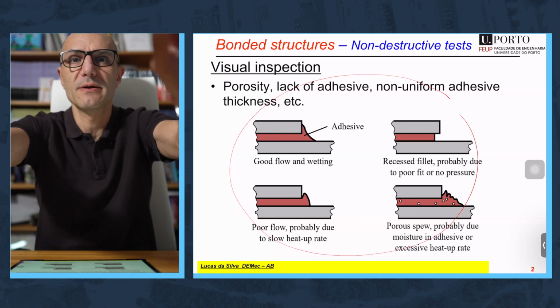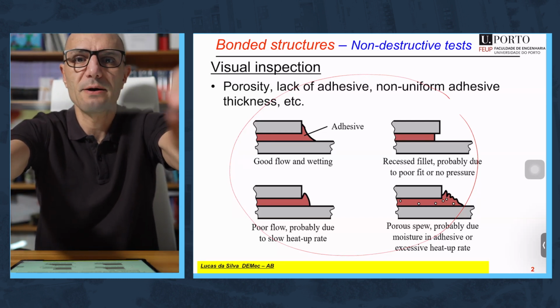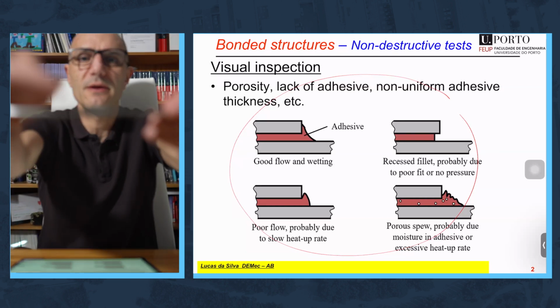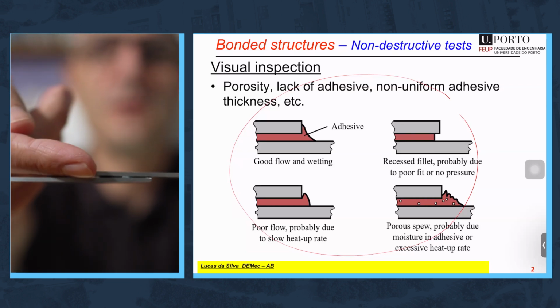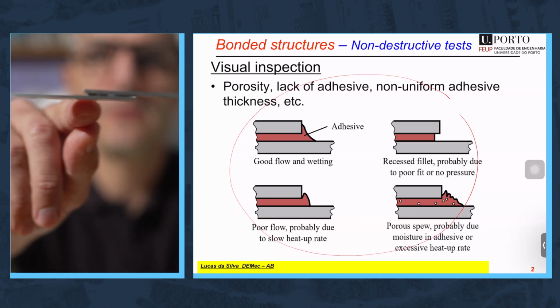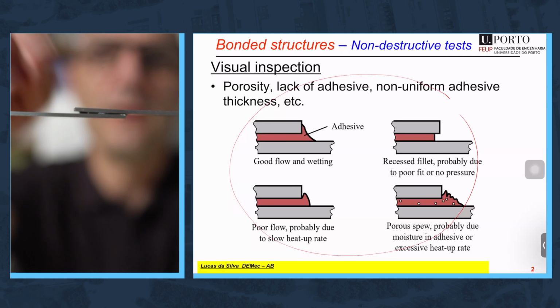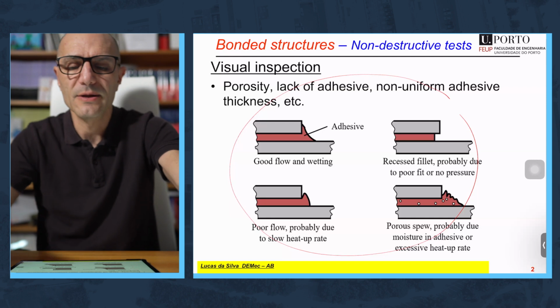For example, this one, can you see? There is a lack of adhesive. On this part, I think it is clearer. There is not enough adhesive. We didn't put enough adhesive here, and the thickness of the adhesive is not uniform along the overlap. Here it's thicker, and here it's thinner. So this is a defective joint, absolutely no doubt.